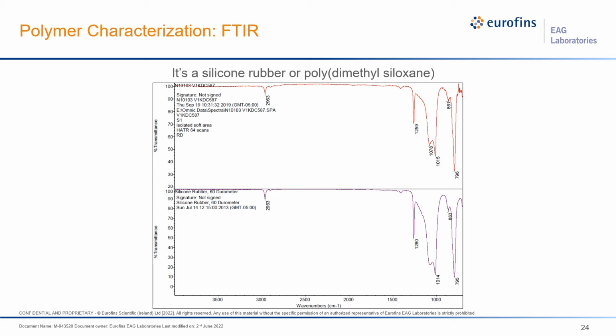So if we look again at our material, this is the soft part of the medical device. On the top, we have our sample, and on the bottom, we have our spectral library match. This is coming up as a silicone rubber or polydimethyl siloxane, also known as PDMS. And when we compare these two spectra, unlike the first case study, this appears to be a very, very good match. So we don't see any additional peaks that are present in the sample spectrum that are not present in the spectral match or vice versa. This leads us to believe that it's a homopolymer, meaning it only contains one sort of monomer unit.